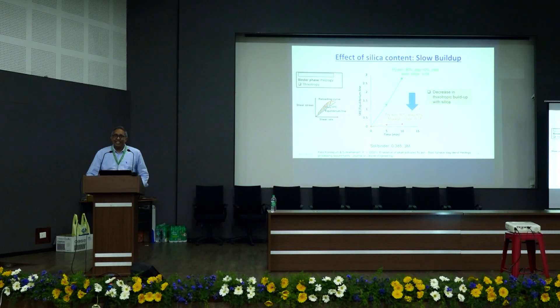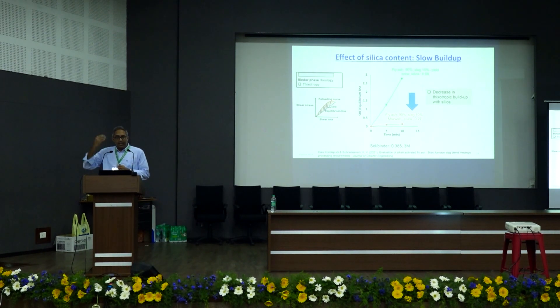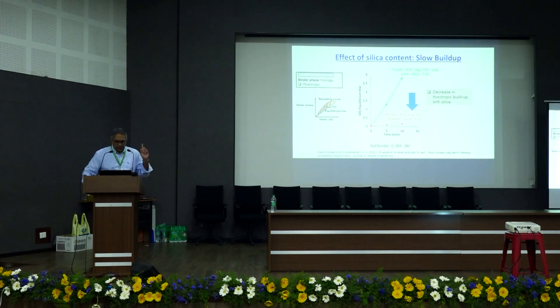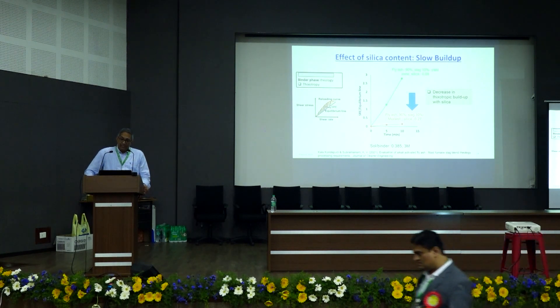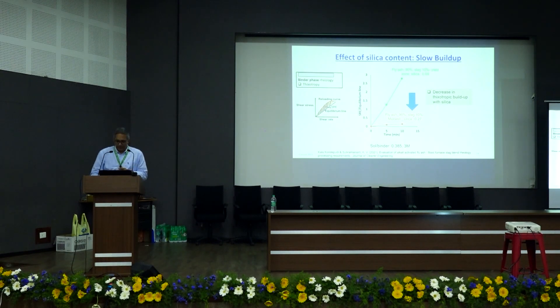There's something else silica does — it kills thixotropy. We measured something called SRE, the Structural Rebuilding Energy: if a material is thixotropic, the SRE will be very high. I shear the liquid, bring it to rest, and see how much effort it takes to disrupt the structure again — that is a measure of SRE. Higher the SRE, more thixotropic the material. What we see is that with very little silica, the SRE is good — the structural rebuilding as a function of time is adequate. The minute I add silica, which I need for strength, the SRE drops. The material is not rebuilding from the inside, so I cannot put another layer on top of it. This is a very challenging binder for printing applications, and that's where rheology control and nanoclays come into play.